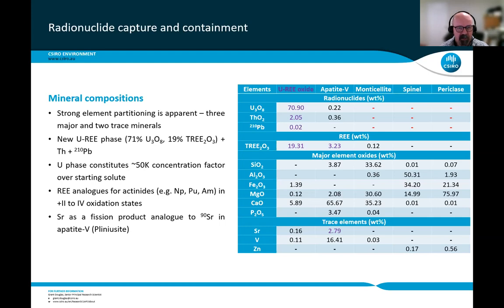The apatite, which is a vanadium apatite, all I really want to highlight here is that it contains about 3% rare earth oxides. But the important thing here is it contains almost 3% strontium. And strontium is important if you're looking at nuclear waste, because strontium-90 is a fission product of the nuclear energy cycle. The other important thing to say here is that now with this U3O8 at around 71%, we've got around a 50,000 concentration factor from that original barren lixiviant that we started with. So an enormous concentration factor.